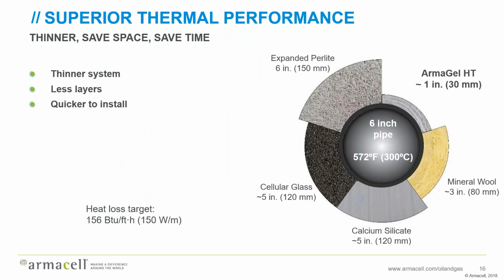To see how that really looks on a pipe, we've got a 6-inch pipe sitting at 572 Fahrenheit, and we've got a heat loss target of 156 BTU per foot hour. That would take something like 6 inches of expanded perlite to reach that heat loss target, or 5 inches of cellular glass or calcium silicate, even 3 inches of mineral wool. But with ArmaGel HT, only 1 inch would be needed. That's an enormous reduction in overall thickness. And less thickness means less weight. It means less product to carry around site. There are a lot of associated benefits with that.